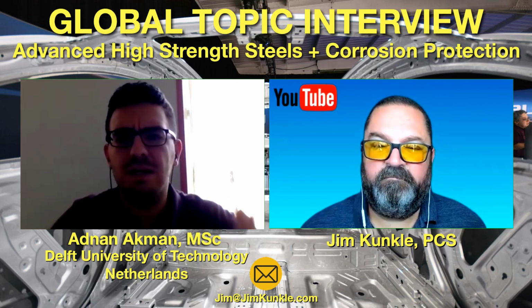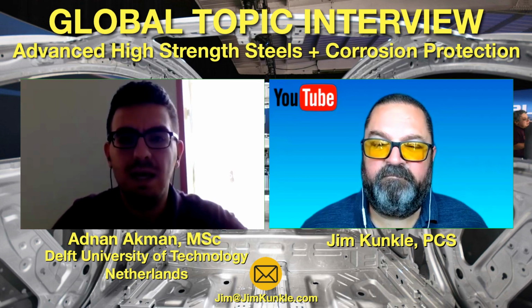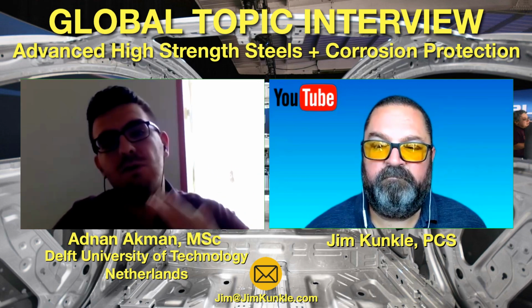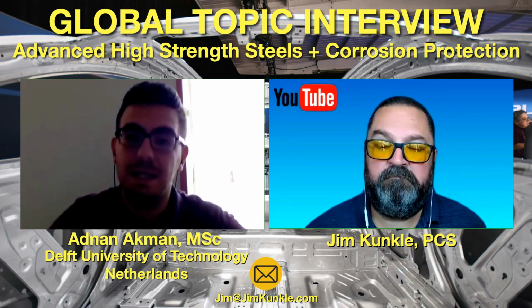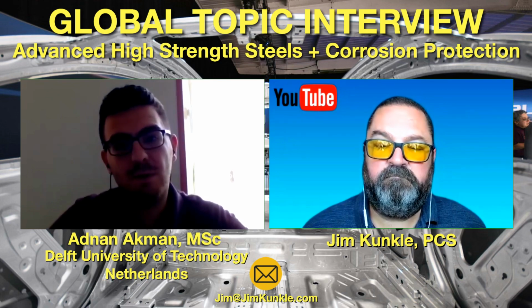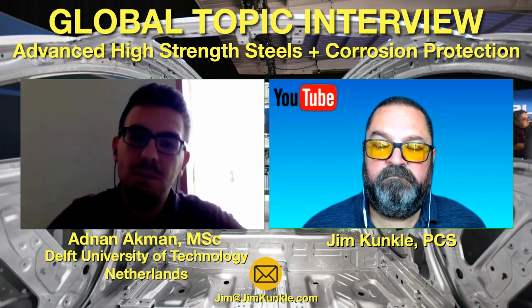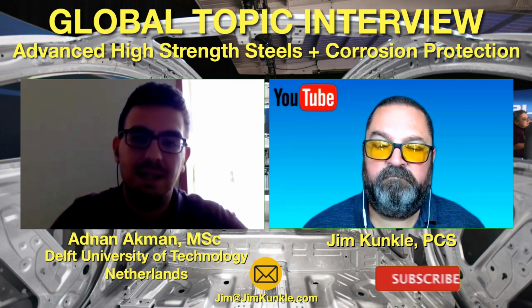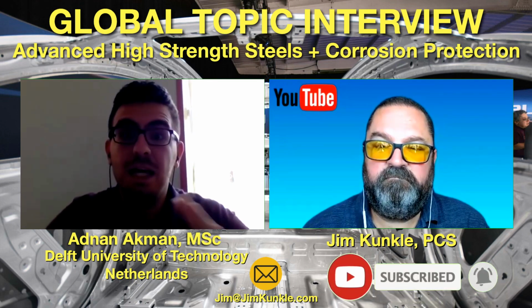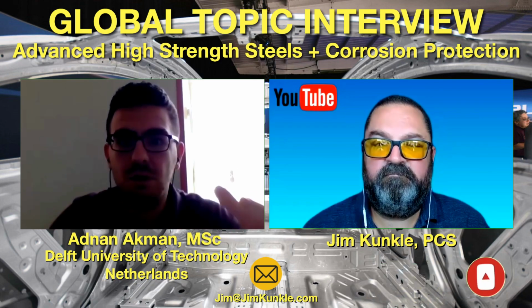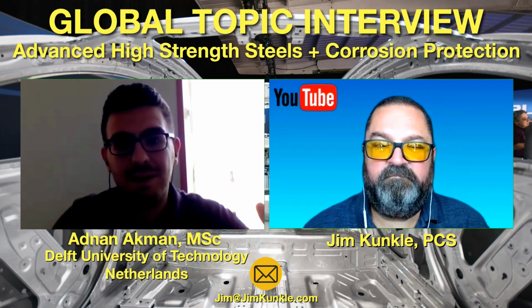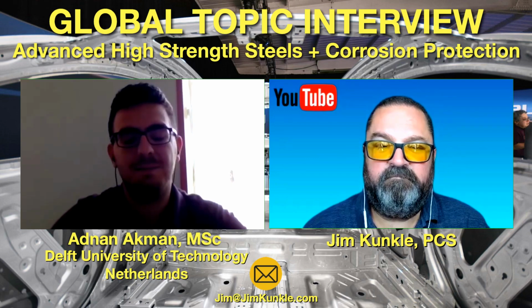If you check the chemical composition of the coating, it is possible to see 9 to 12% bulk iron in your coating. But the aim of the coating is to increase formability and corrosion resistance of the steel, like previous techniques. But the problem in this technique is that if you cannot control the zinc content, the formability of the steel will be quite hard.